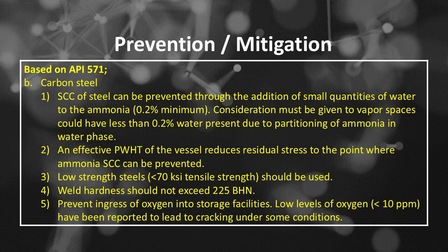Number 5, prevent ingress of oxygen into storage facilities. Low levels of oxygen, less than 10 ppm, have been reported to lead to cracking under some conditions.